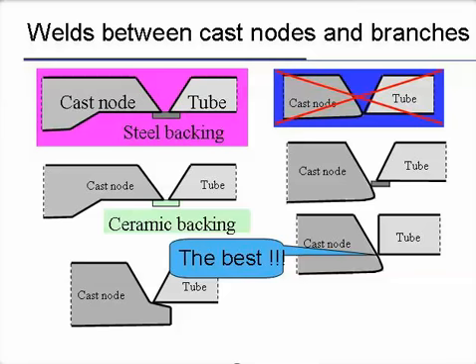So when you do this, well, guess what? You don't have any problem with the node. Effectively, the cast node is very good. You get the crack like here, where you have the casting here and the tube here, and you get the crack in between. So again, the weld is the part that is the weakest. You have defects in the cast node, but it's more fatigue resistant, so you don't have any problem with the cast node actually.